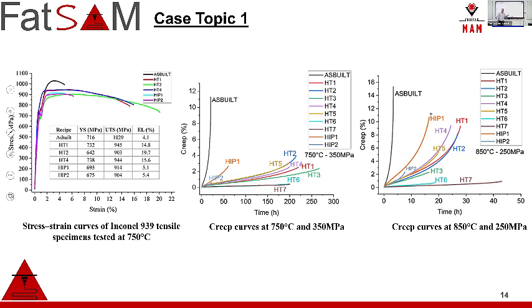As I said before, 939 can be used in different parts. I'm interested in NGV parts, where temperatures are much higher and loads are extremely low. You are not looking for the life you obtain in the creep test; you are looking for the creep percentage or plastic deformation after rupture in these materials. In the case of HT7, it is less than 1% creep strain after 200 hours, which is very good, and not comparable but close to cast NGV values if you decrease the applied load during the creep condition. This test is at 750 Celsius.